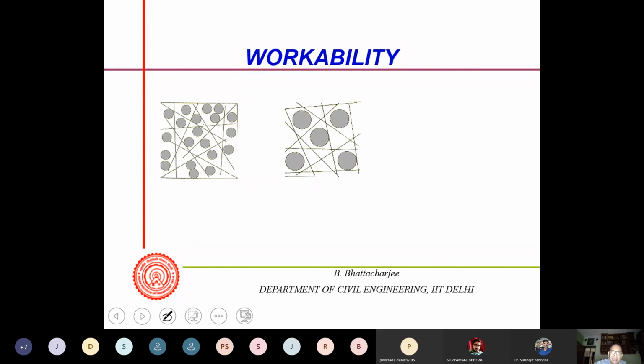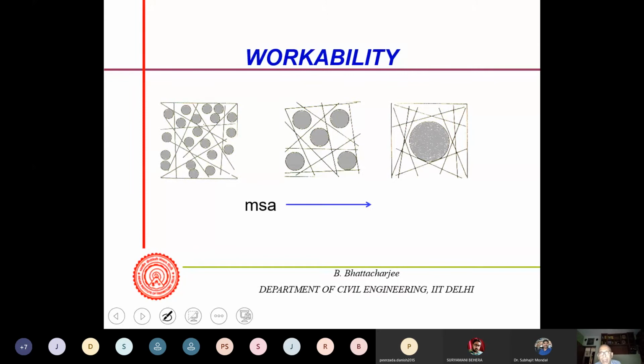If your aggregate size is large, fiber tend to come closer. Large size aggregate, fiber tend to come closer. And they form a ball. That's called balling. So maximum size of aggregate has got a role. Therefore, paste content has to be high. MSA should be low. And about 70% should be paste.